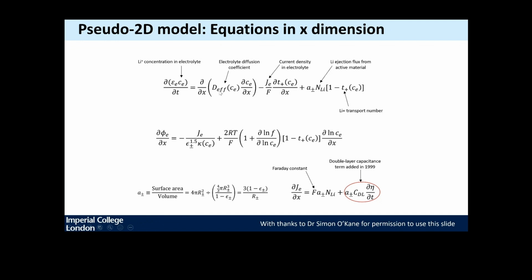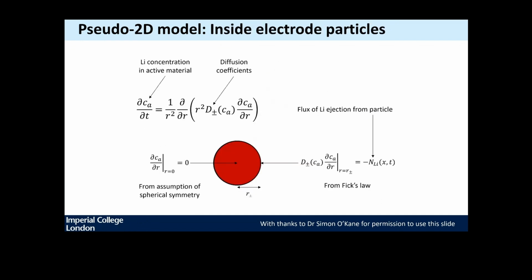So in principle, you should measure this at different temperatures. If we go back to the diffusion inside the electrode, again, you have a diffusion coefficient, which is now for the Li0 inside the electrode. So you should try to measure that. It will also depend on temperature, and more importantly, it actually depends on state of charge.